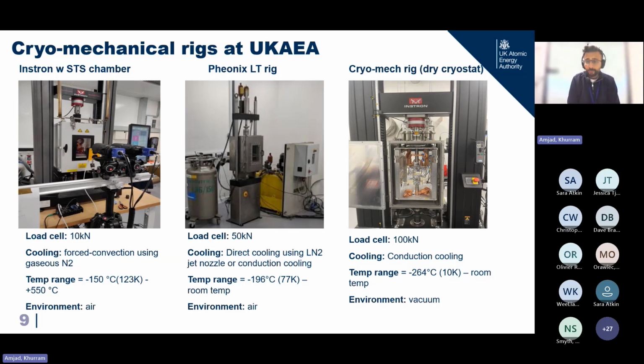And the third rig we have got has a 100 kilonewton load cell. It's a cryogen free rig, which can go down to theoretically 10 Kelvin. It uses cryo coolers to cool the sample through conduction. And the environment is, of course, at such low temperatures, you can't do any testing other than in vacuum. And I have some preliminary results that I'll present from this rig as well.